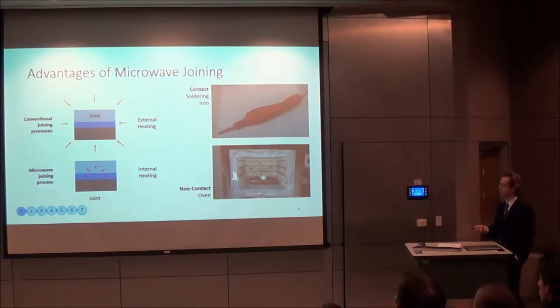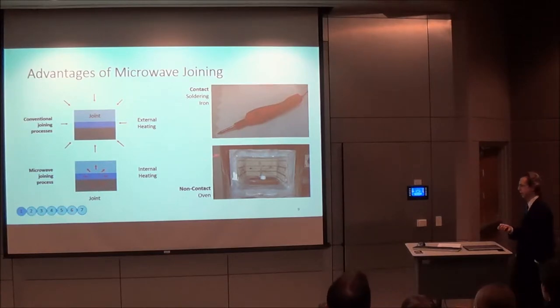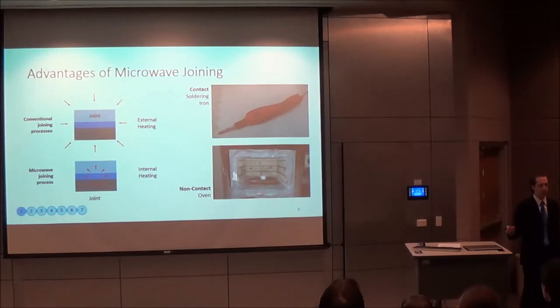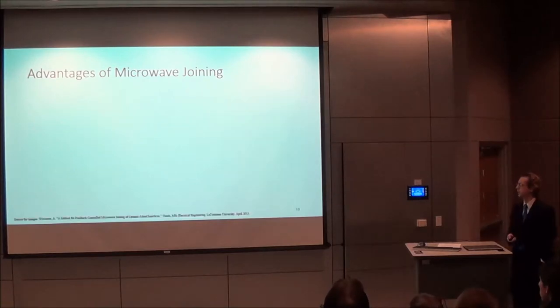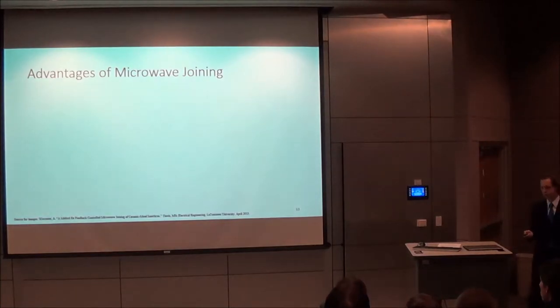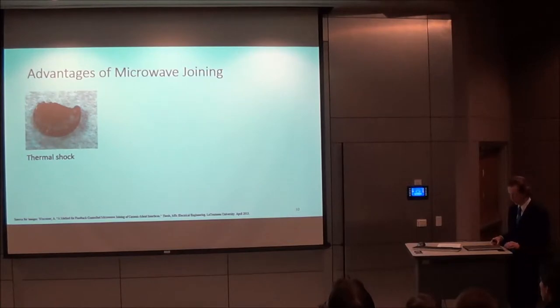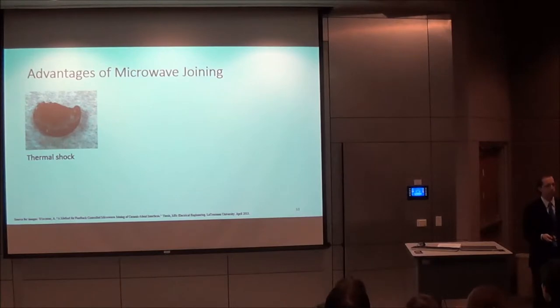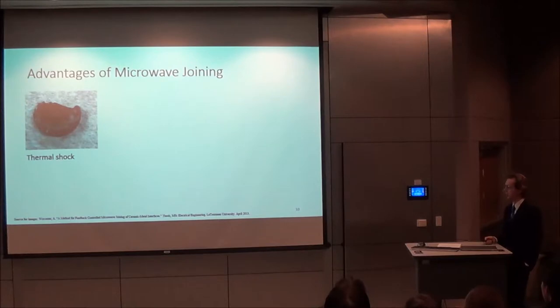And basically, microwave heating gives you the advantage of a contact process by being efficient and applying the heat directly to a particular part, but also the flexibility of a non-contact process by not being as limited, perhaps, to joint configurations that a contact process may be limited by. And so, particularly for joining of ceramics to metals, there are several advantages that come out and why we would use microwave heat. For one, ceramics are prone to thermal shock. And if they're heated too rapidly, if the thermal gradient is too great, they can